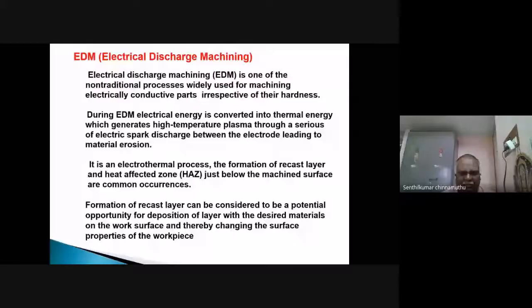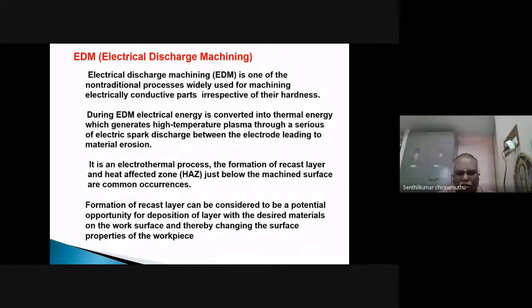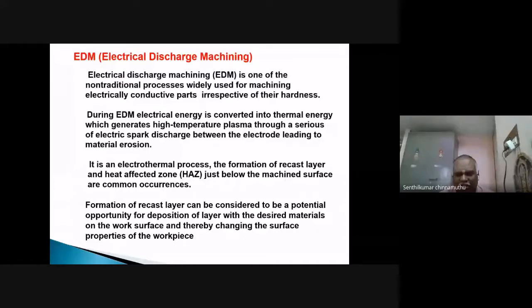In this process, the formation of a recast layer in the zone just below the machined surface is a common occurrence. See, the formation of the recast layer on the surface of the workpiece is considered to be a potential opportunity for researchers to deposit a layer of the desired materials. You might have seen, after completing the machining process, if you cut and look through the microstructure, a heat affected zone or recast layer.